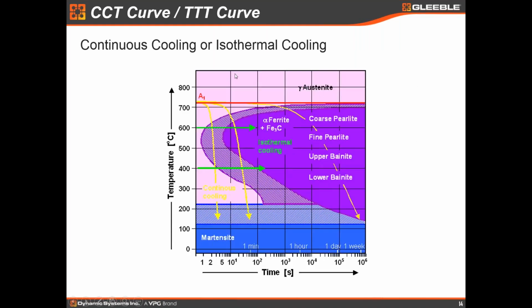Another way to plot it here is a little more realistic curve, not quite so schematic. Again, it shows different cooling rates, slower cooling rates, faster cooling rates, or you can also have isothermal holds. So I can cool down to 600 and hold for a certain amount of time, or at 400 and hold for a certain amount of time, like is illustrated with these green arrows. And I can predict then, based on the previous work that was done in the dilatometer, what phases I'm going to get in that steel alloy.